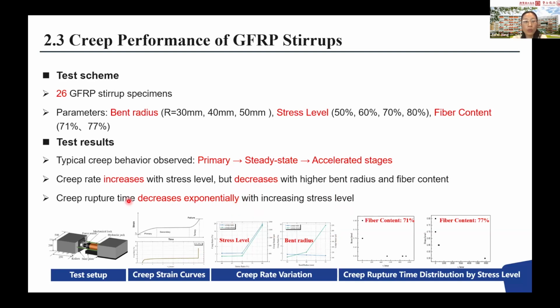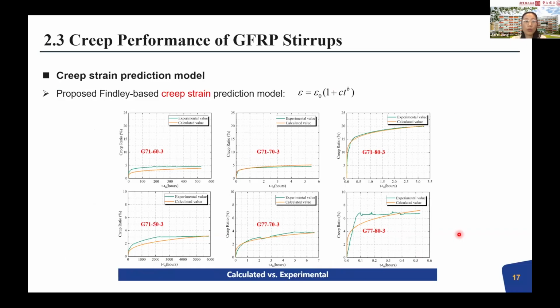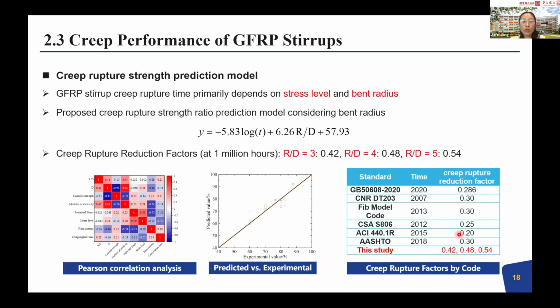increased. And also, we can say that creep rupture time decreases exponentially with increased stress level. This shows the reduction of the stress level versus the rupture time for 2 types of FRP stirrups. And based on this behavior, we developed the creep strain model to evaluate the long-term straining behavior for FRP stirrups. And also, we do the rupture strength ratio prediction, which is correlated with time and also correlated with